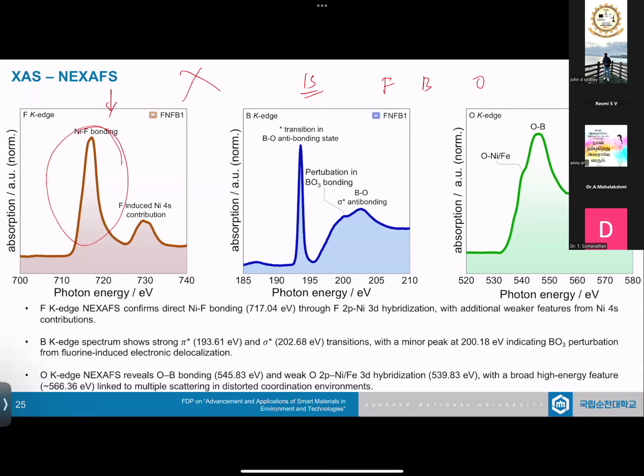But through this, we confirm that the fluorine is bonded to a metal atom. And which metal atom, again, we know. This confirmed the presence of fluorine, giving us strong evidence that the fluorine is really present in the system, chemically bonded, altering the system in all its nature.